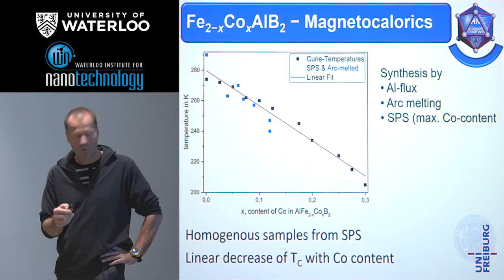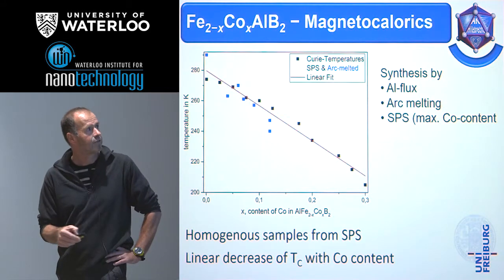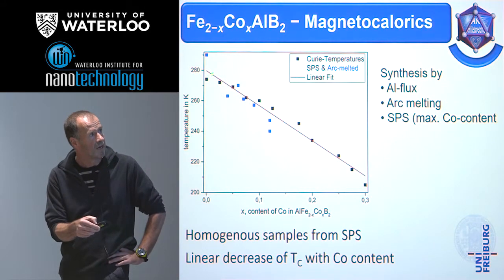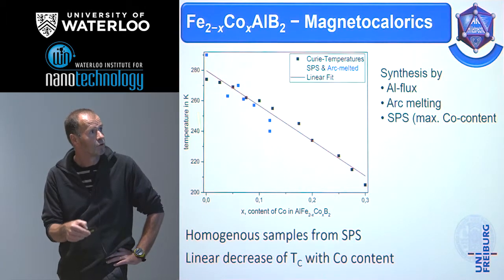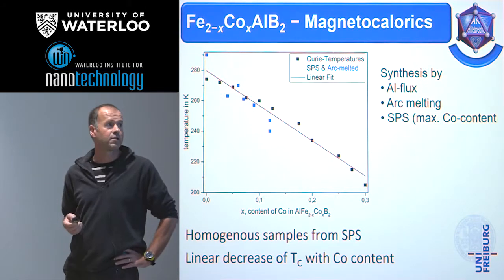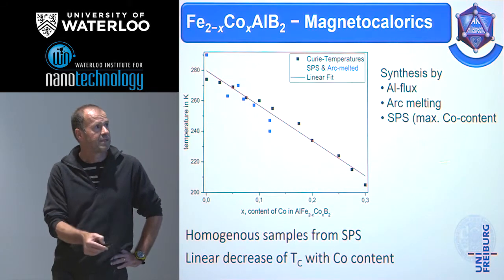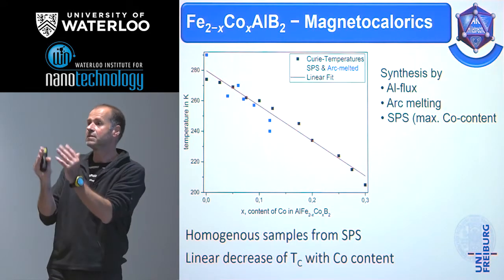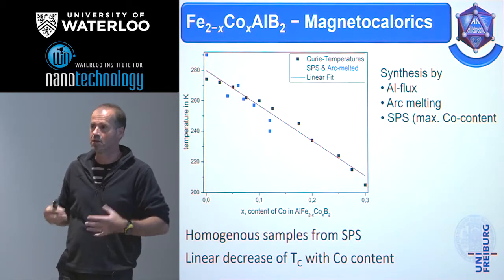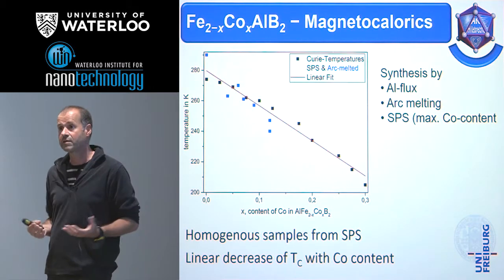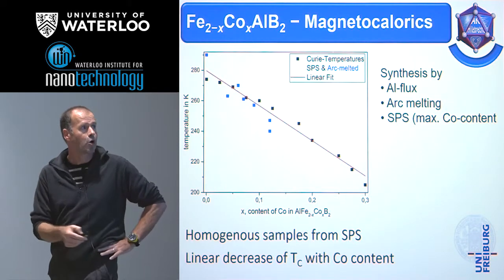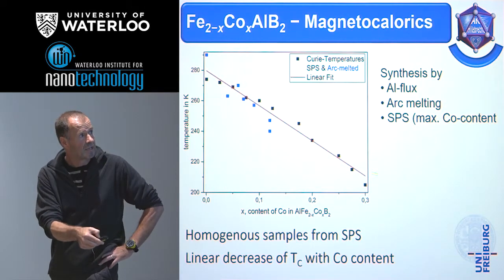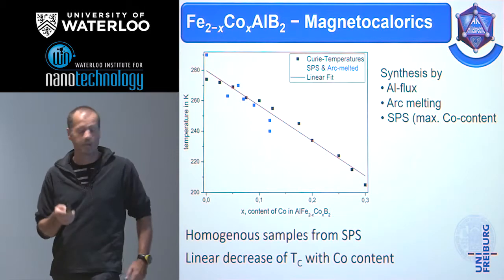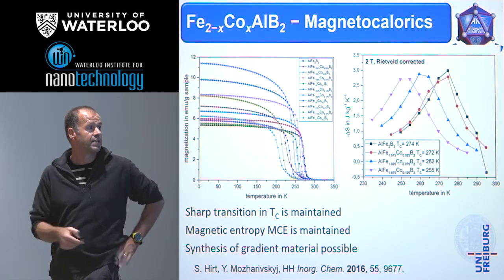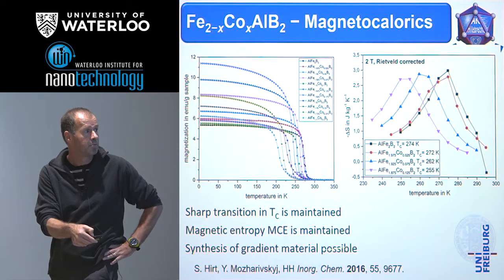And it's really quite an interesting development that we showed a linear dependency of the cobalt content to the Curie temperature. Another advantage of our SPS synthesis is that we get bulk material, which is easy to handle, which shows no cracks, and which can also show a continuous content of cobalt. That means we can also manage to get a gradient material.